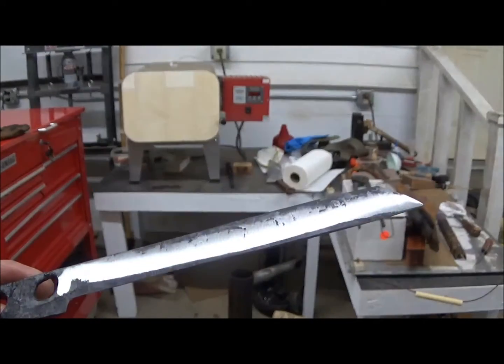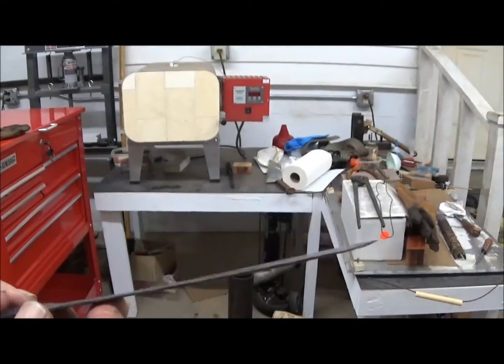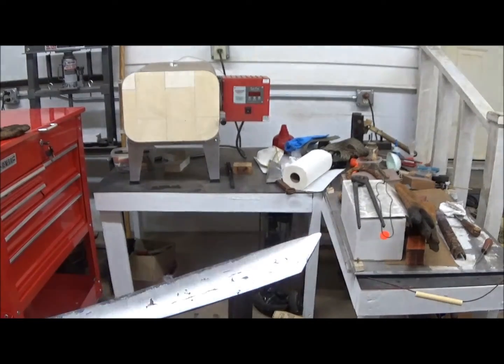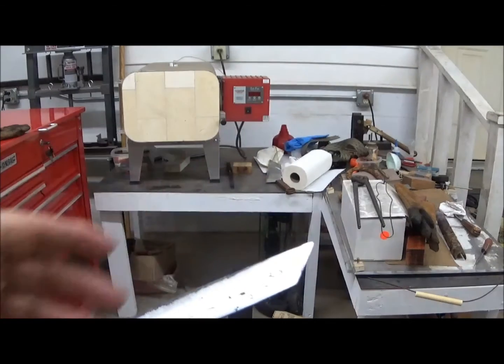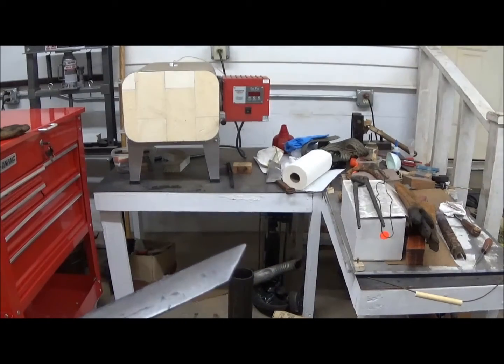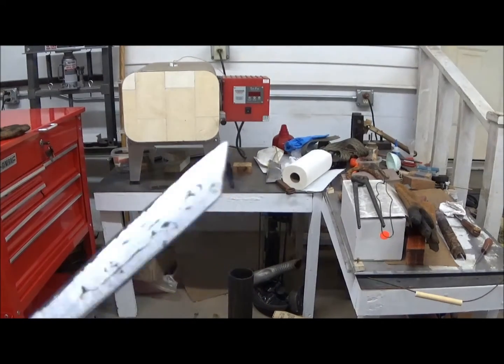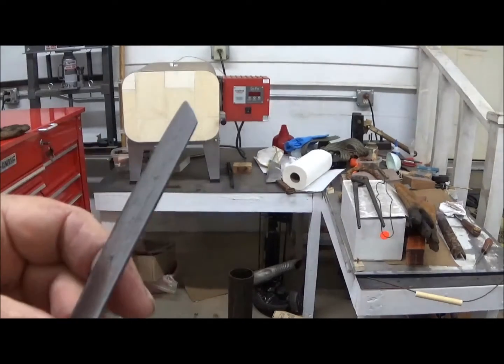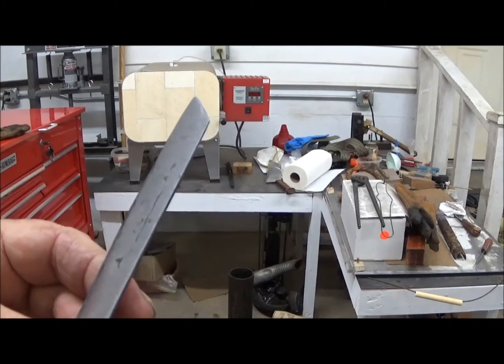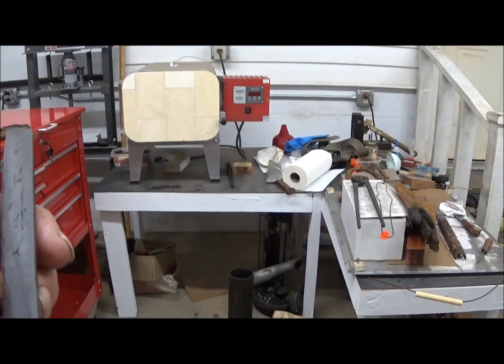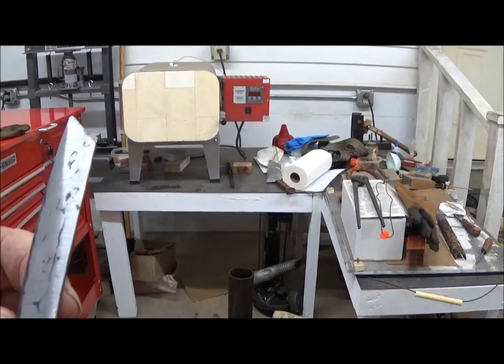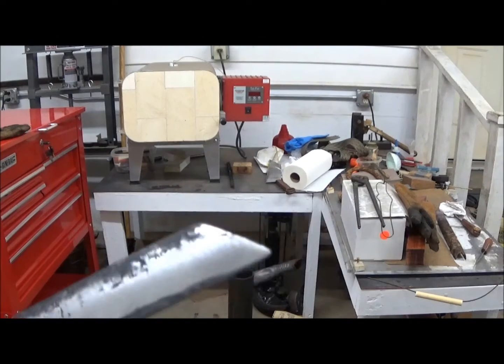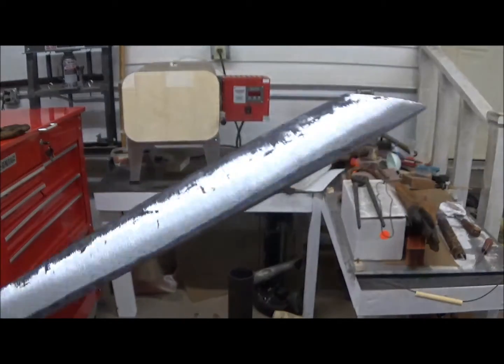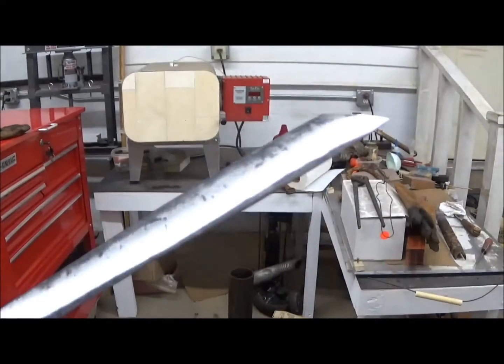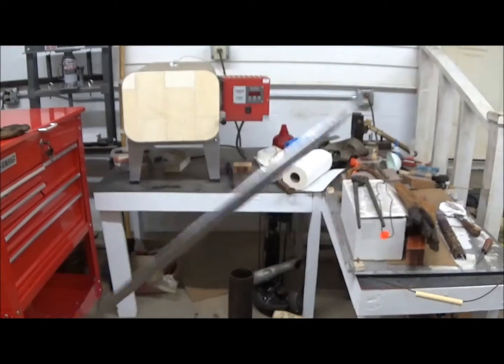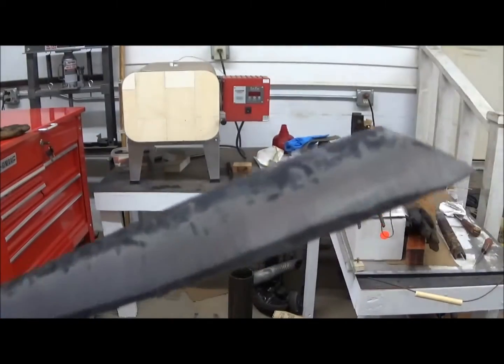The blade is grinding dead soft. It did not take the temper. The crack is not serious. It's not deep in the steel, it's just a minor surface thing. So that I think I can work with. So we're going to put it back in the furnace, heat it again, 1850 degrees this time, not hold it for quite so long because we're getting pretty thin now, and do an oil quench.